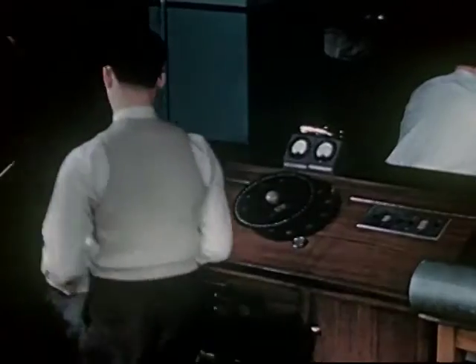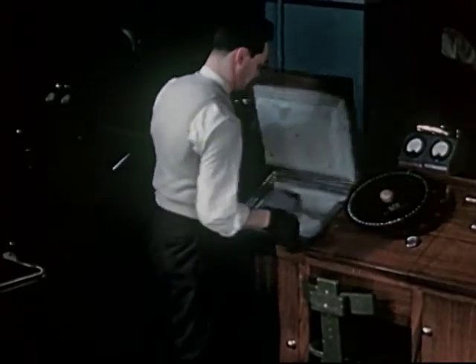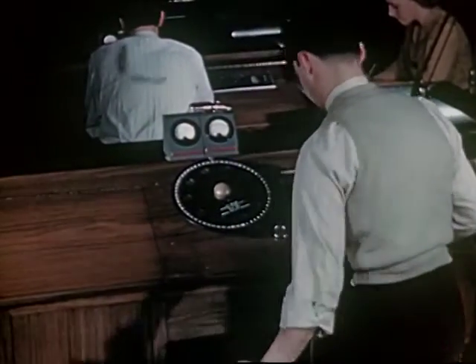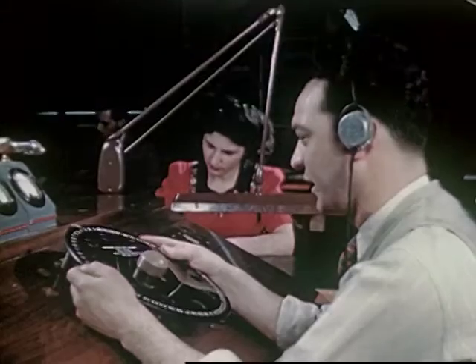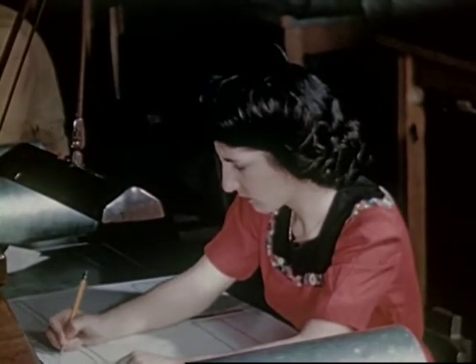The activity and frequency of each crystal are measured and recorded while it is being subjected to temperatures ranging from -55 to +90 degrees centigrade. Air circulating over dry ice in one part of the box simulates temperatures in the stratosphere. Heating units in another part of the box bring the temperature up to heights much greater than those expected under normal operating conditions. The performance of each crystal is measured every 2 degrees over the temperature range, and a complete record of it is made.